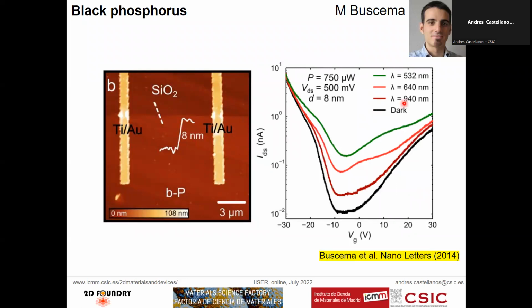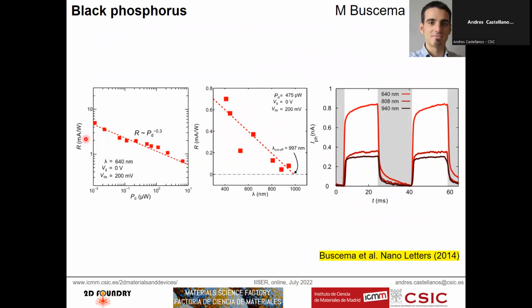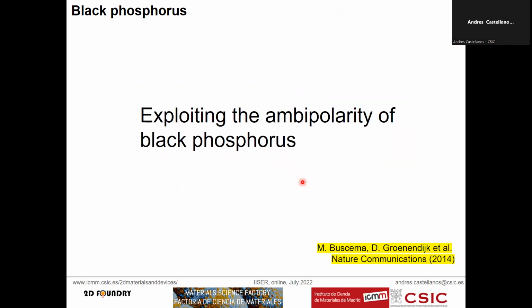As a photodetector, this material is very nice because you can get responsivity in both the electron and the hole regime. In bulk, when you have a multilayer of black phosphorus, the band gap is around 0.35 electron volts, so a very narrow band gap. It means that you can go all the way to the near infrared and even beyond and still have a response there. Regarding the responsivity, the device is not that highly responsive, but it's much faster than many other devices that we studied so far. But for sure, the best thing about black phosphorus is that it's ambipolar.